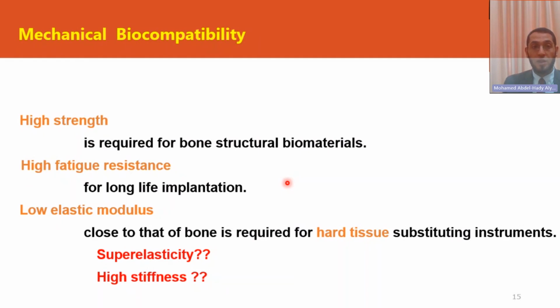Okay, so if we go back to the other properties needed for biomedical alloys, some mechanical properties are needed to fulfill the application. Different applications, different requirements. Sometimes, or in the majority of cases, we need high strength and high fatigue resistance, and one of the important things that we will show you today is low elastic modulus. That is because the bone itself is created very elastic. So if the alloy that will replace bone does not have good elasticity matching that of bone, there is a phenomenon called stress shielding. There is a mismatch in the elastic property, so a big problem happens after implantation. Most of the surgeons know this problem: after implantation, the bone itself loses its density and the implant becomes loose, and we have to make revision surgery, with very many complications.